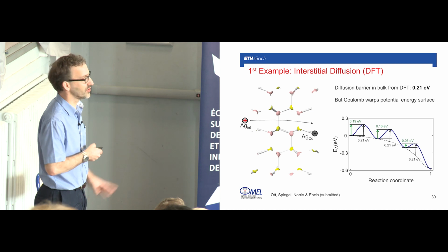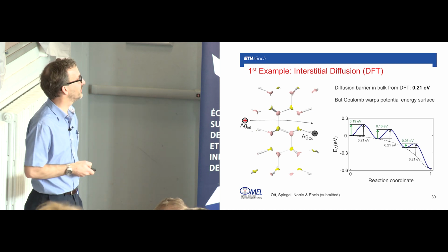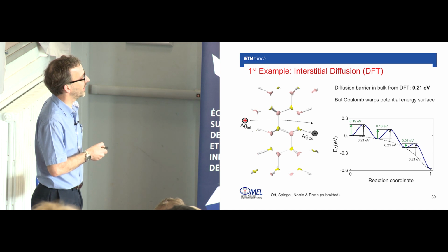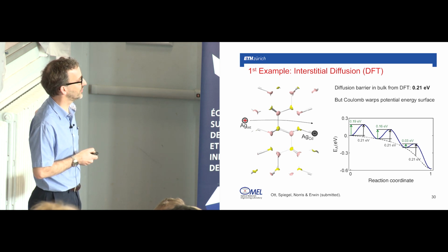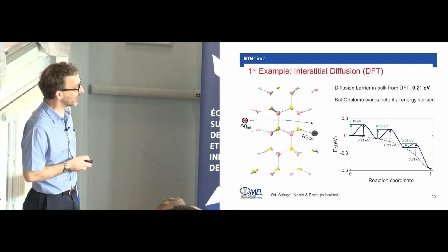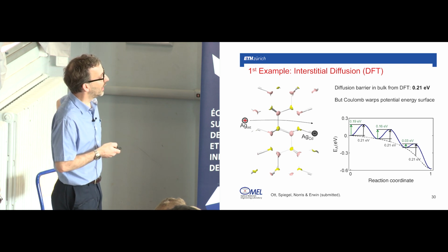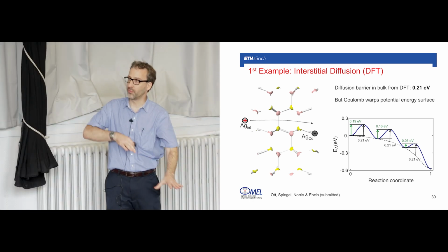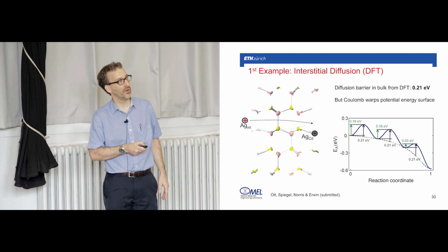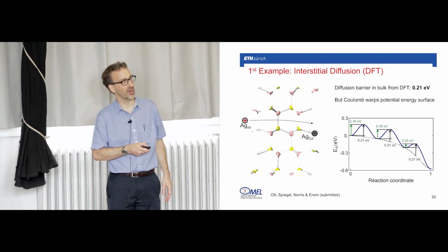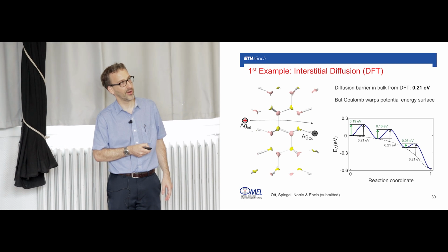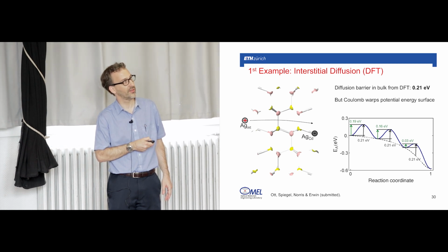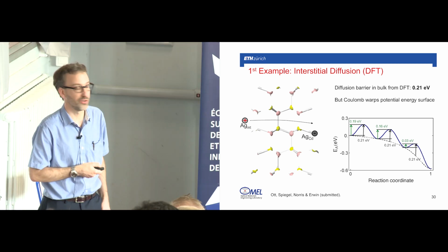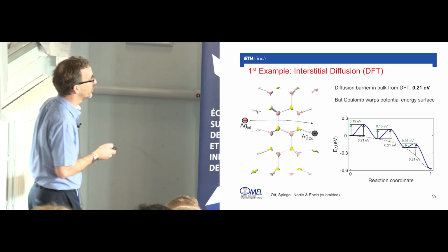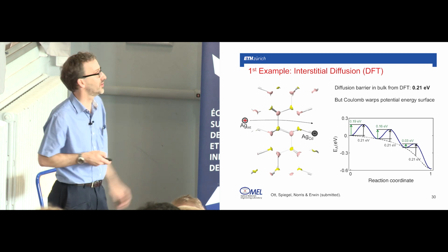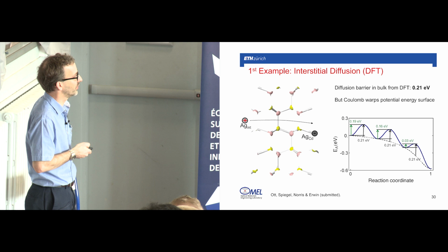The first one is interstitial diffusion. So I told you silver is a very fast diffuser in cadmium selenide. So you can calculate the diffusion barrier of this interstitial hopping from interstitial site to interstitial site. And the barrier is about 0.2 eV. But if you have any Coulomb interactions, of course, this will warp this potential energy surface. So for example, if you already have a substitutional silver that's negatively charged, then this barrier, as this thing diffuses, will get smaller and smaller as this thing gets sucked in towards this negatively charged substitutional. So that's one example. Basically, diffusion will occur quickly: a silver interstitial will move towards a silver substitutional.